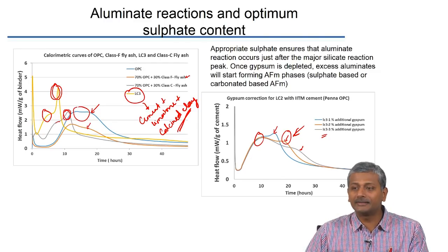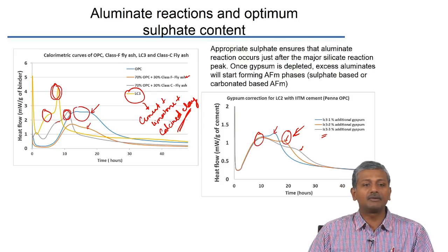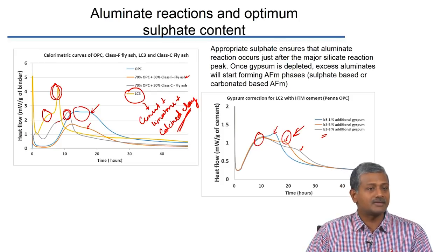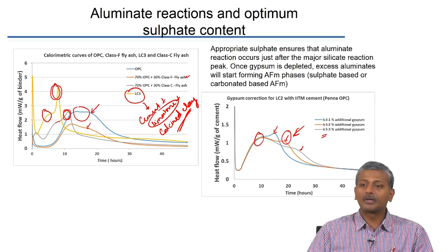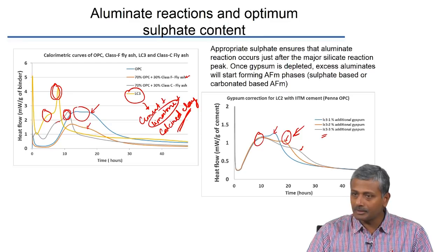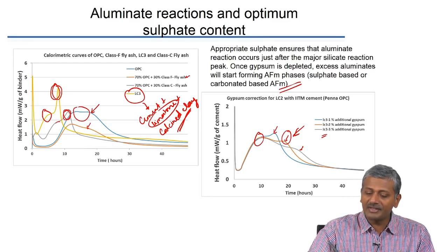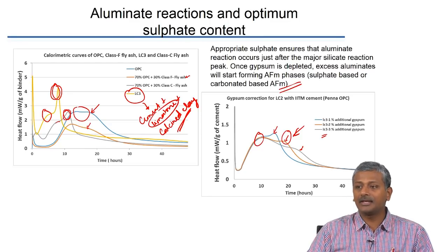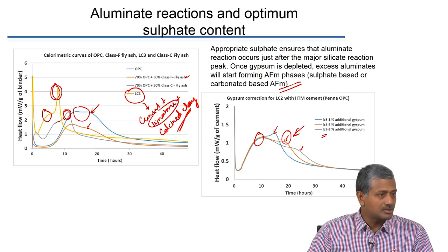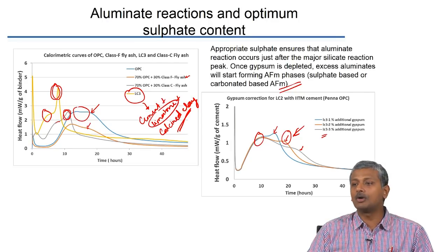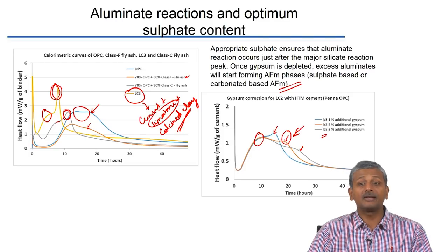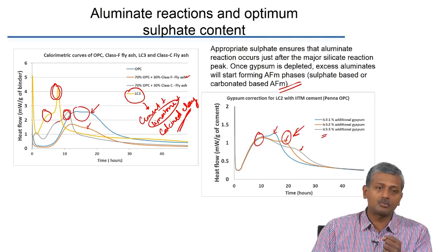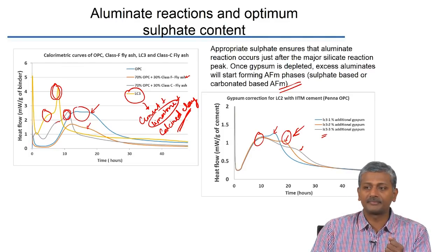In the LC3 system, since limestone contributes carbonate, the AFM phases are not restricted only to monosulphate. A phase called monocarbonate can also form with the LC3 system, which is an additional hydration product specific to this system.